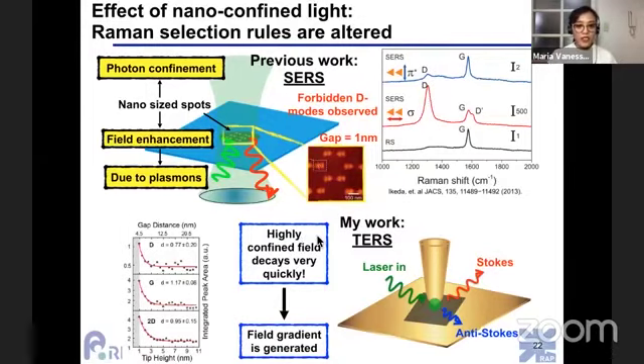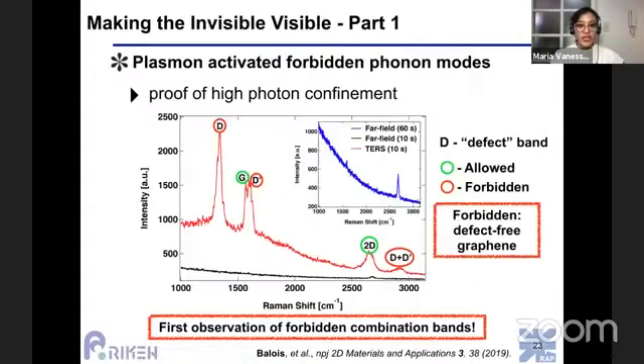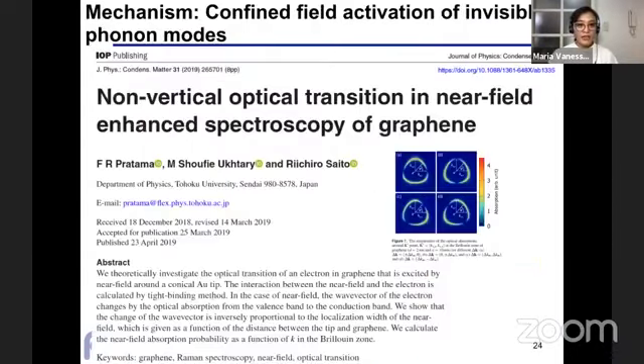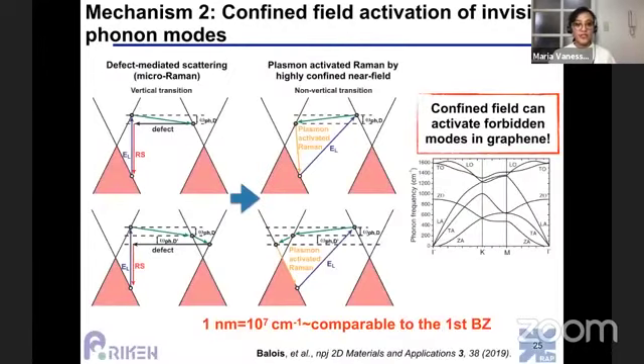We think that this is because of the highly confined field that decays very quickly. This is a field gradient, which in turn also changes the Raman selection rules, which means that we indeed are now making the invisible visible, because phonon modes which are not supposed to exist are starting to show themselves, particularly these defect related peaks, which are not supposed to be there because our sample is defect free. We think that this is due to the non-vertical optical transitions caused by our near-field system, which activates these forbidden modes and also detects them.